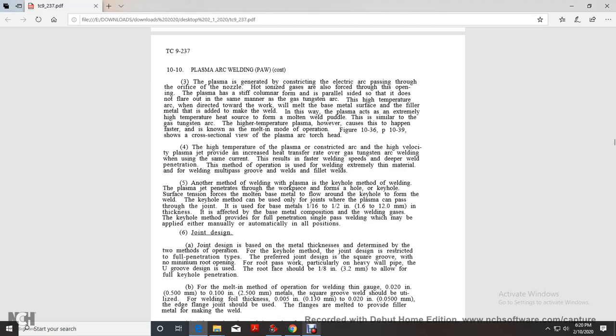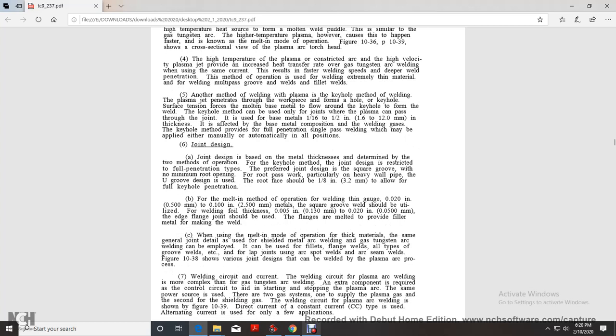The keyhole method provides full penetration single pass welding, which may be applied manually or automatically in all positions. Joint design is based on the metal thickness and determined by the two methods of operation. For the keyhole method, the joint design restricted to full penetration is preferred, with a square groove joint design with no minimum root opening for the root pass, particularly on heavy wall pipe. With the U groove design, the root face should be 1/8 of an inch to allow